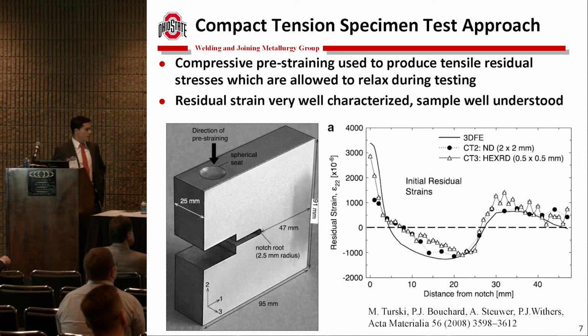And so the sample geometry, of course, is extremely common. And in this work, there's a lot of characterization of the residual strain. So this is an example of that. They created a 3D finite element model, and with a small gauge section of high energy X-rays, we're able to observe residual strain very similar to what they predicted in their modeling.